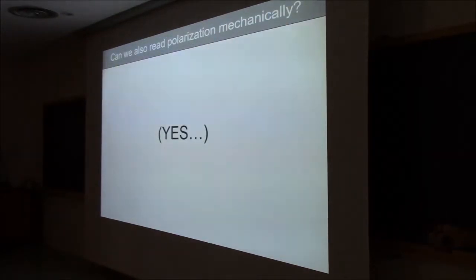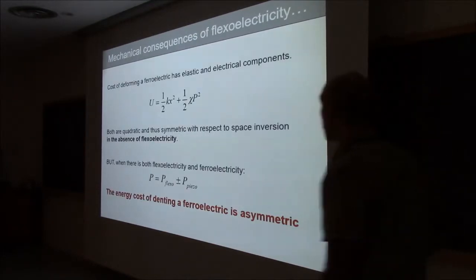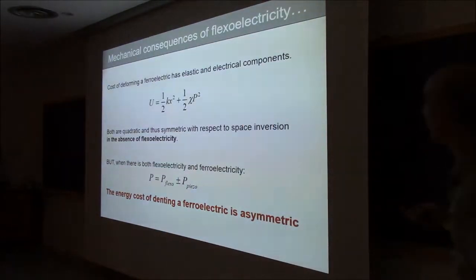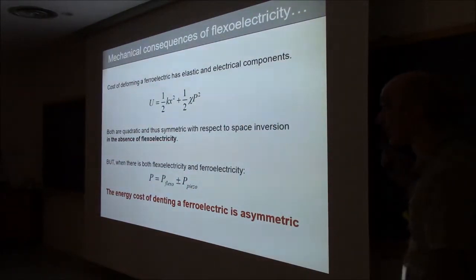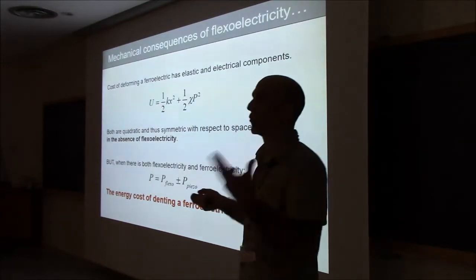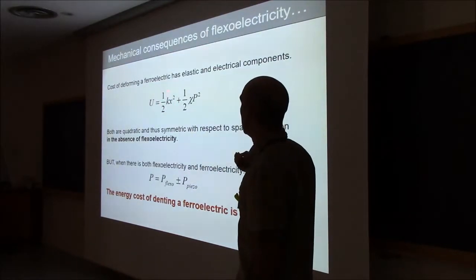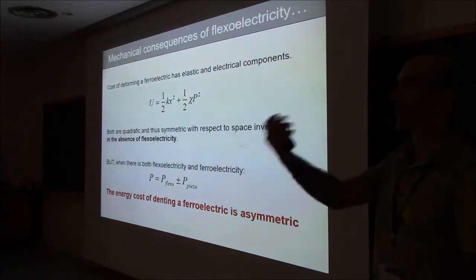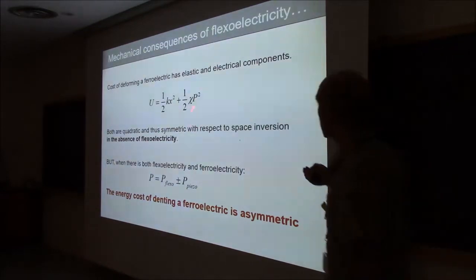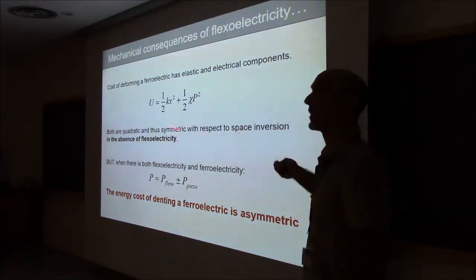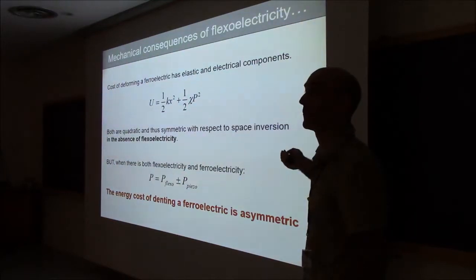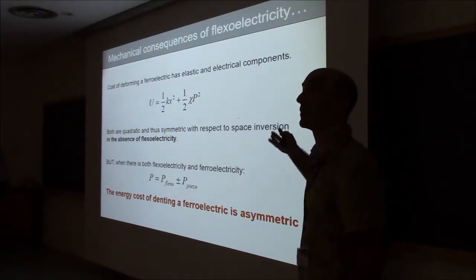Obviously, the next thing that you want to see is, can we also read the polarization by flexoelectric means? And the answer, of course, is we can. And the reason why we can, we think, is the following. If you take any material and you try to induce some deformation, the energy cost of the deformation is Hooke's law. It's proportional to the elastic constant times the square of the deformation. If your material polarizes when you try to deform it, you also have to pay an electrostatic cost, which is proportional to P squared, the square of the polarization. Basically, this is the depolarizing field.